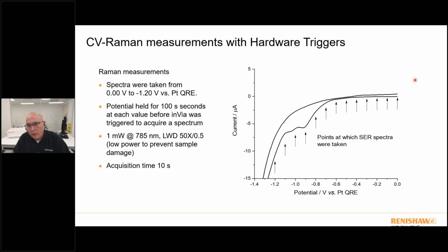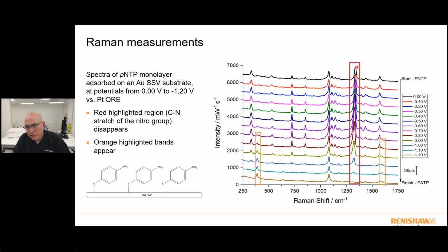So with the hardware triggering, we were going to be driving from 0 volt down to minus 1.2 volt and wanted to collect spectra at 0.1 volt increments along that CV gram. So in each of these cases, we would hold for 100 seconds and then initiate a low power 1 milliwatt 785 measurement for 10 seconds and acquire the Raman spectral data. And as we're starting to do that, we're starting to see the NTP bands, the C-N band kind of disappearing and starting to see some of these additional bands reappear. So we're watching that reduction occur all fully automatic using the hardware triggering.